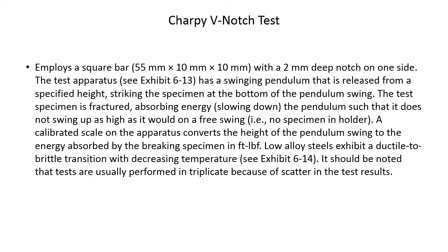Here's one you're going to run across a lot as a CWI. The Charpy V-notch test. The Charpy V-notch test employs a square bar 55 millimeters by 10 millimeters by 10 millimeters with a 2 millimeter deep notch on one side.